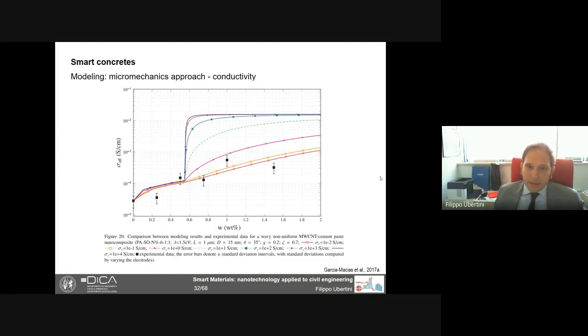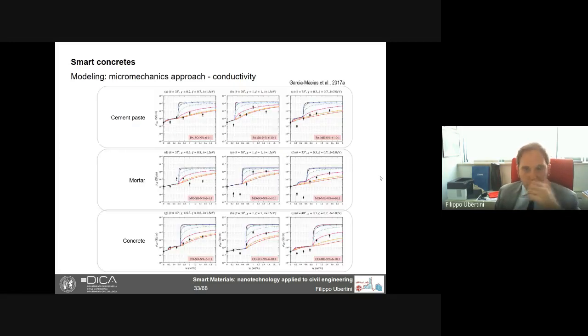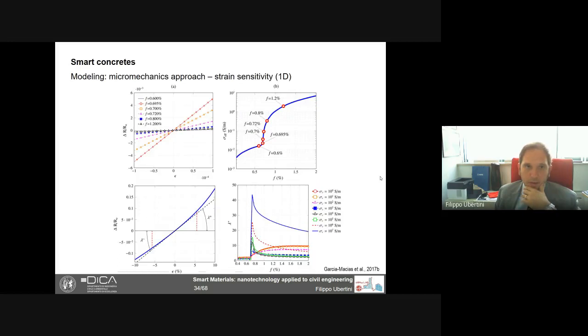To really get close to the experiments, as you see in these results, we need to add also the bundles. If we add the parameters of the bundles, then we can really interpret the behavior of this composite. That was our result in a paper by Garcia Macias and co-authors in 2017. And this was systematically demonstrated for cement paste, mortar, and concrete.